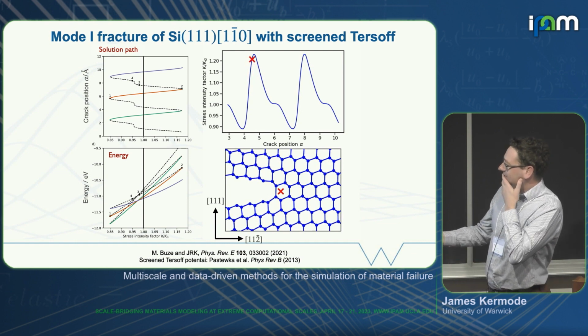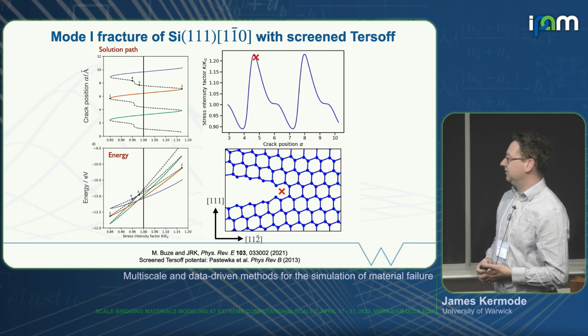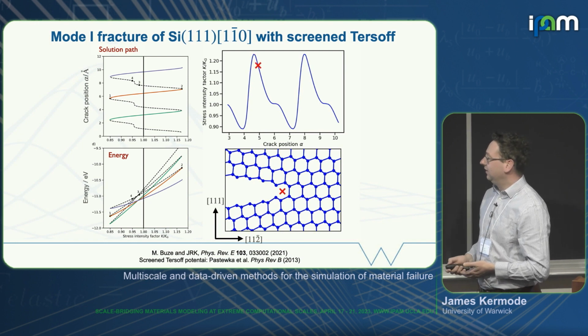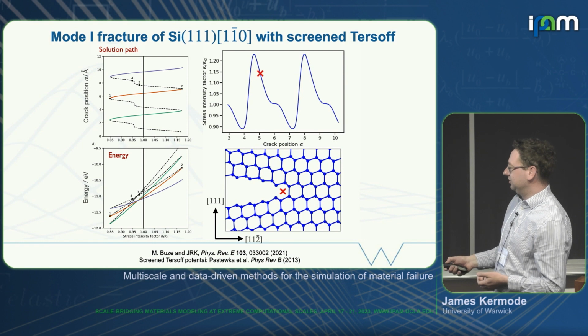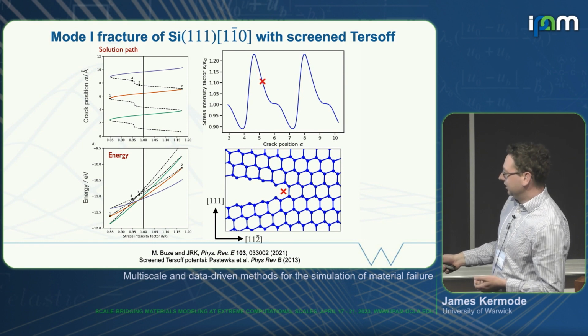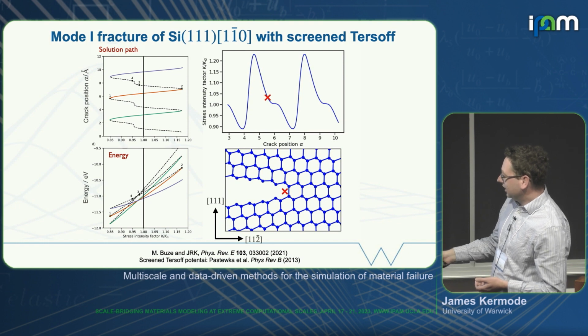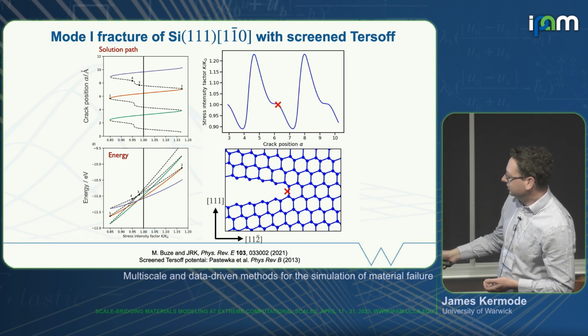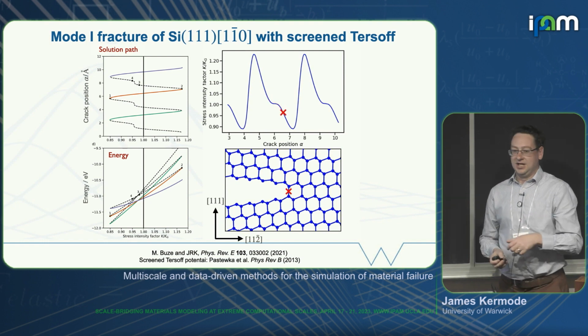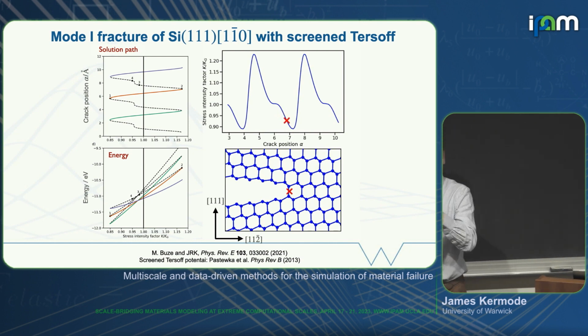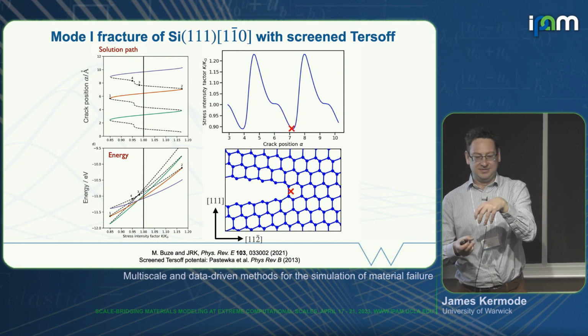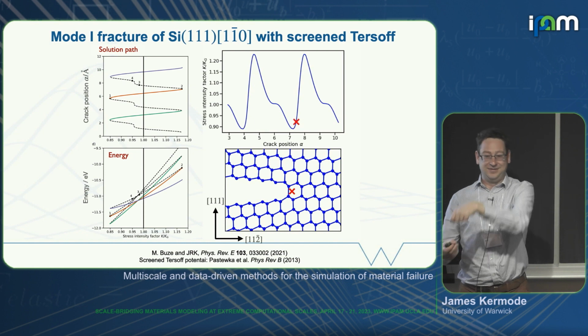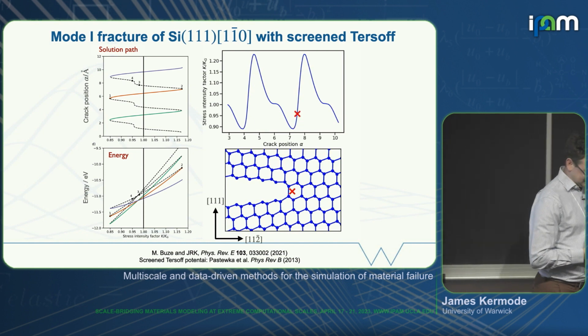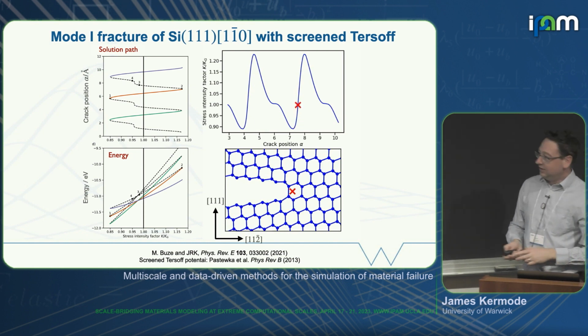And then there's this interesting feature down here in the unstable part of the solution path, which corresponds to the bond behind the crack tip. So you see that this bond has opened already, but now keep your eyes on it as we go through this kink here, and you can see a further relaxation, and that's because there's a many-body potential. It's not just a nearest neighbor interaction, so there's still some interaction there, and we see that finally kind of giving up as we go through that kink in the solution path.